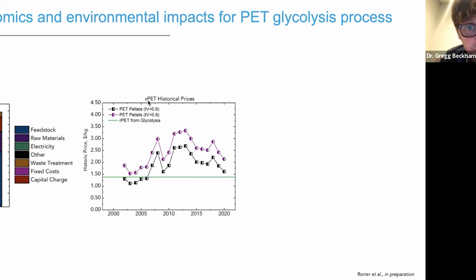And what's shown here is virgin PET historical prices at different intrinsic viscosities, so useful for fibers, useful for bottles. And this is in green, again, in a conservative case where we think the rPET from glycolysis could sit. And you can see more or less it's always below virgin PET prices. And again, thinking about reducing the feedstock dramatically, you could even reduce this more.